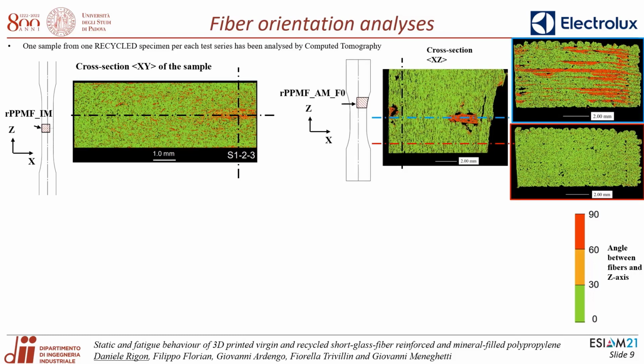Let's see now the F0 specimen. The sample, in this case, was taken at the end of the gauge part of the specimen in order to highlight the detrimental features caused by the automated scanning strategies proposed by the software. In fact, in this case, after having filled the layer, the extruder should interrupt the flow of the material and move to the next region. But actually, a trickle of material remains and generates these strips with fibers oriented at 90 degrees with respect to the load applied. As can be seen in the XY section, these path changes occur in the same position in each layer, generating a weak point of the specimen.